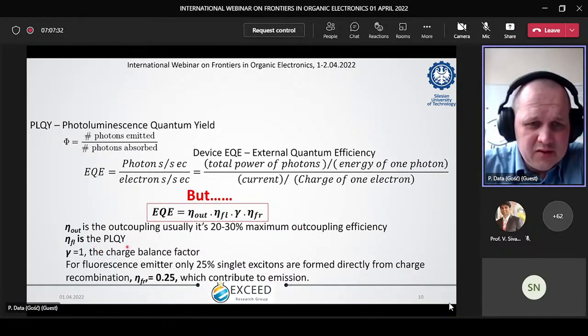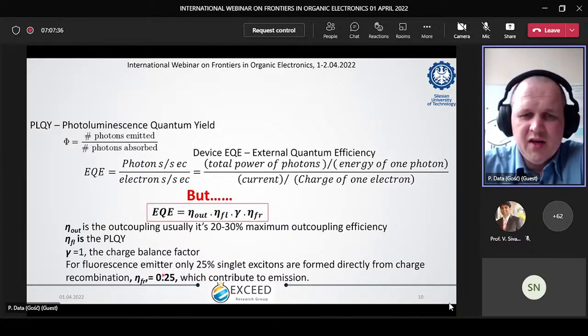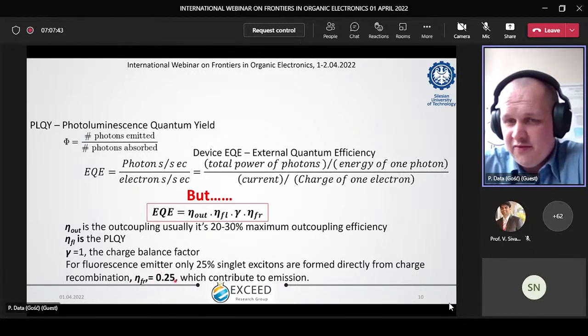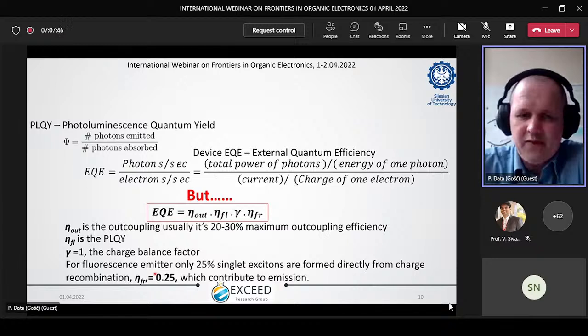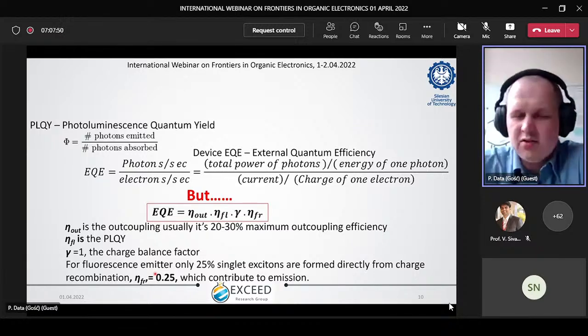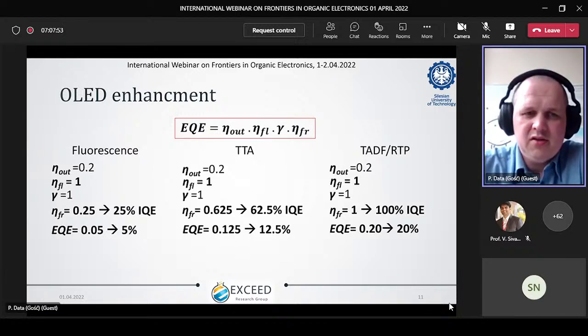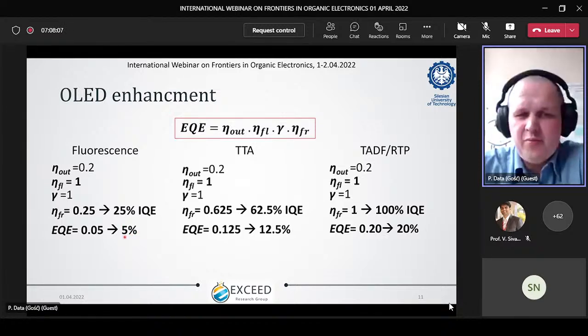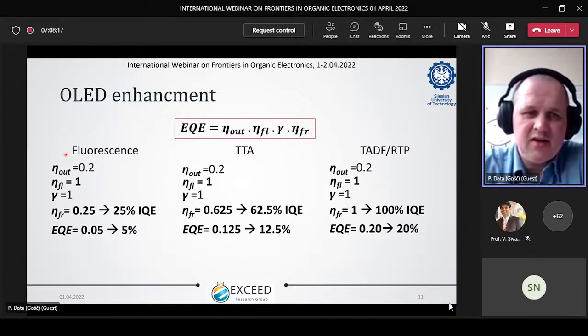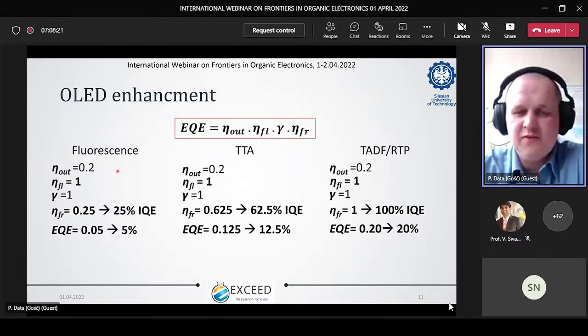One of the important factors which you need to know here is this fraction of the excited state. So in the case of a typical fluorescence emitter, our fraction is 25%, so 0.25. If we think about TADF, it can go for 1, so 100%. If we compare those different emissive processes, you can find that for normal fluorescence emitters, our EQE can go up to 5% if we assume that our outcoupling factor is 0.2. Again, in normal typical devices without any optical boosting, the outcoupling is between 0.2, so 20%, and 30%.